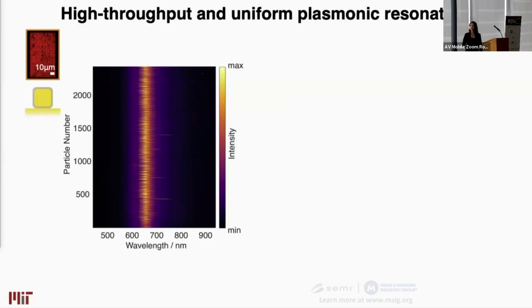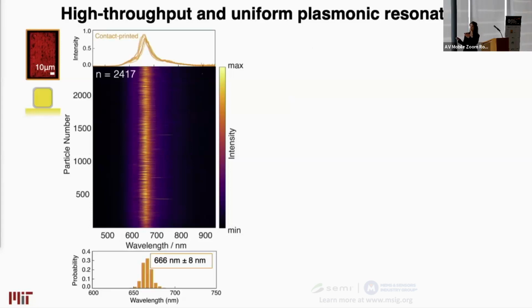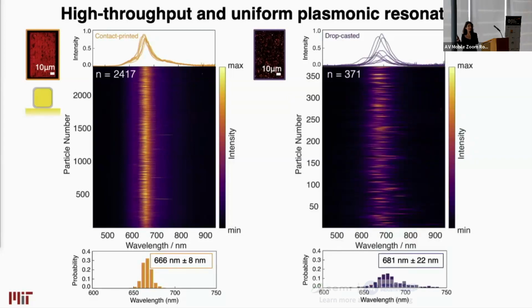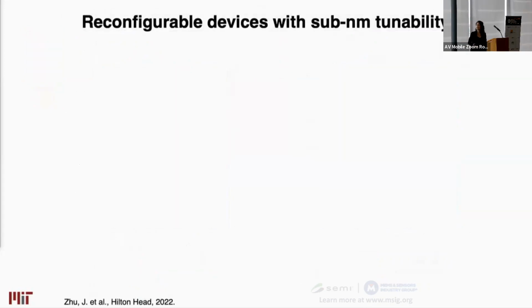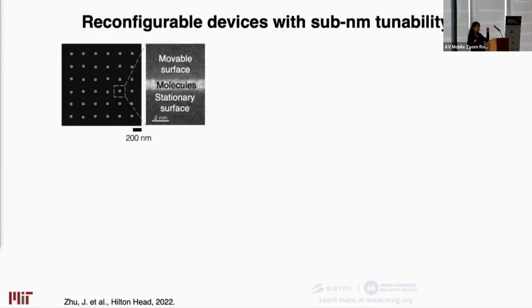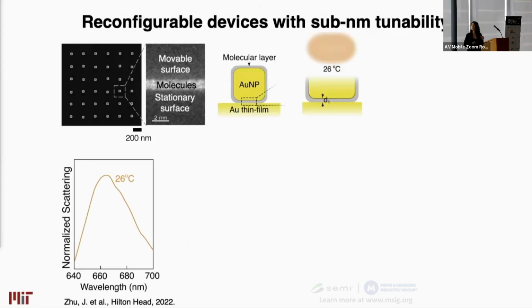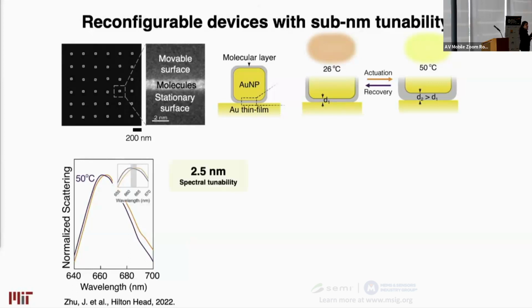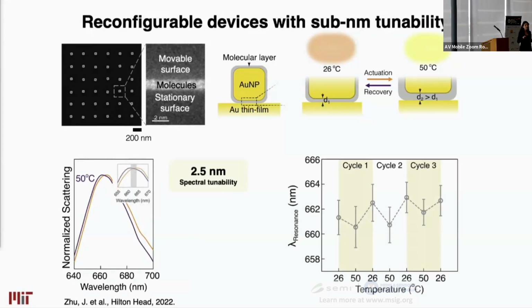The resonators show very reliable and consistent response, and that's a huge improvement compared to what you would get through conventional fabrication techniques for this type of resonator. If I take one of these structures and cut through it again, you can see the metal-molecule-metal geometry. If we thermally actuate these devices, just to probe the extent of modulation we can get, you can see that by changing the temperature by just 25 degrees, we can change the spectral response by about 2.5 nanometers, and this can be done reversibly. This is very detectable optically, and that corresponds to only about 30 picometer modulation of the gap.